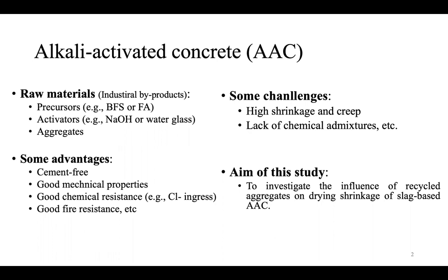Alkali-activated concrete has multiple advantages, for instance, good mechanical properties, chemical resistance, and fire resistance. Of course, it also has some weak points, possibly high shrinkage and creep. Another critical point is that most chemical admixtures developed or used for conventional concrete will not function properly in alkali-activated concrete due to its high alkalinity.